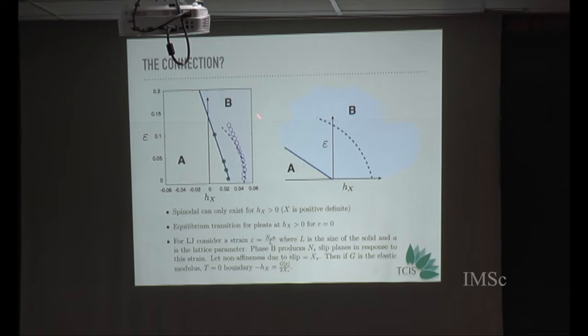So this is the case for pleating. Here is the case for solids. So we saw this dynamical line. We are actually calculating this equilibrium line right now. And this equilibrium transition is between two very interesting phases. A is a phase which is what we think is a solid, that it resists shear. So you take a solid and you shear it, it resists. That is phase A. Phase B is a solid which, when you shear it, automatically rearranges and gets rid of the shear.